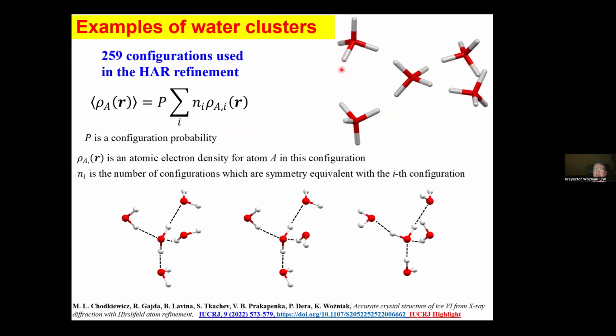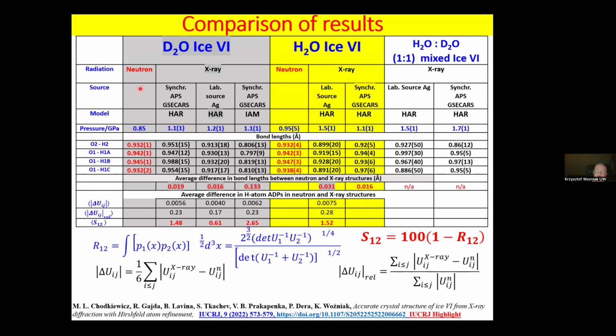But what we did in our Hirshfeld atom refinement was to convolute this average crystal structure, this average cluster of molecules, into 259 different configurations. And you have an illustration of 3 of them in this figure. For each of them, we calculated a separate wave function, and we averaged the wave functions, and then got the average electron density and applied Fourier transformation of this average electron density and got average aspherical atomic scattering, Hirshfeld scattering factors, and used them in the refinement.